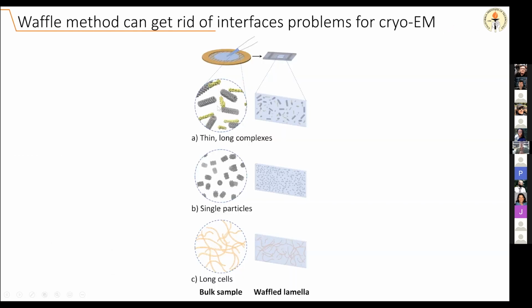So why this waffle method can be not only interesting to weird people like me that do tomography on plant samples, but they can also be interesting for structural biologists. Since we're high pressure freezing our sample, we don't have any air in our system, so we're not worried about any air-water interface. And so the idea would be to generate waffle lamellae on high pressure frozen solutions of your protein of interest. And then single particle analysis can be either performed on the lamella, or tomography can be performed on these lamellae containing the little proteins.